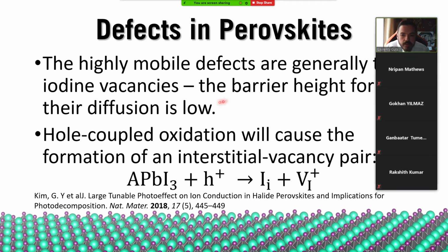And the last thing to say about defects in general is we have one defect that is very problematic. This is currently a hot topic of research, and that is hole-based oxidation of the material. So basically we create an interstitial iodine and a charged iodine vacancy, and this is called the charged Frenkel defect. And the problem here, we believe, is actually these interstitial iodines. They migrate to the surface, and then the surface degrades. That's basically what we believe is the issue with these.